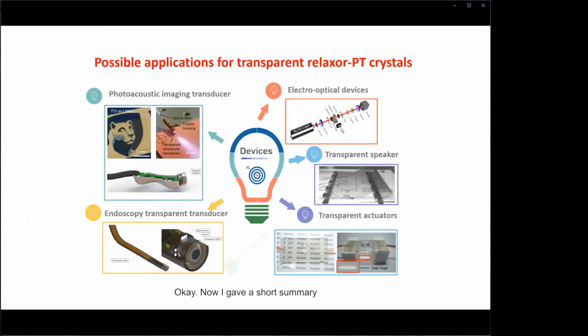Okay, now I give a short summary of the work related to transparent Relaxor-PT crystals. In this work, we report a simple approach of using AC electric fields to simultaneously achieve near-perfect transparency and enhance the piezoelectricity for rhombohedral PMN-PT crystals. And we think that such transparent crystals are expected to find a wide range of applications in electro-optical mechanically coupled devices, such as photoacoustic imaging transducers as shown here, electro-optic modulator, transparent speaker, and also transparent actuators.